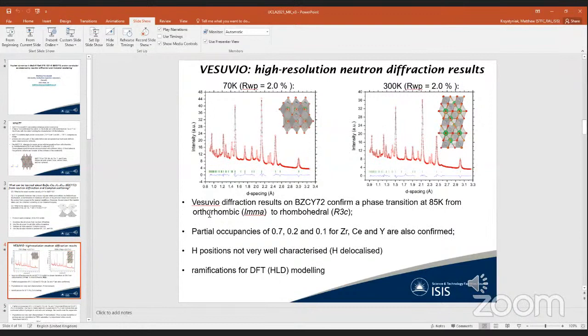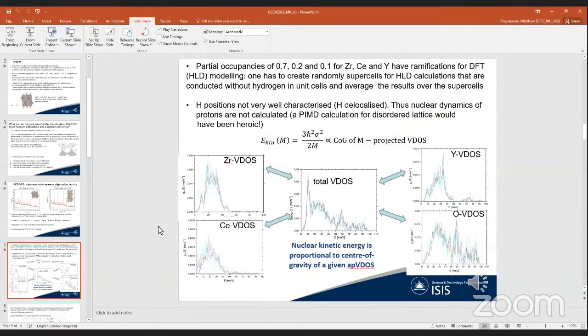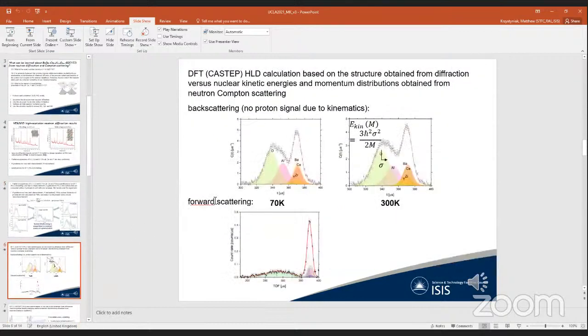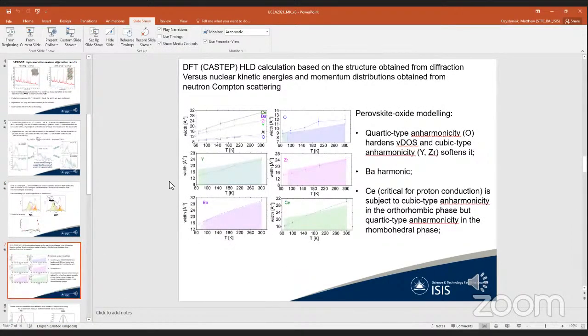We just use the structure without hydrogen, accounting for hydrogen indirectly by lattice distortions in the modeling, and try to come up with the predictions for the vibrational density of states, partial vibrational densities of states of zirconium, cerium, yttrium, oxygen, and barium in this material. And what we are interested in are the centers of gravity of those, because they are proportional to nuclear kinetic energies that can be directly measured by time of flight neutron Compton scattering and compared with the experimental results. When we do it, we can plot the width of momentum distribution, which is a square root of kinetic energies as a function of temperature, and then compare it with lattice dynamics prediction.